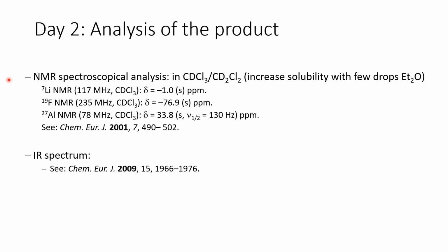The product should be further analyzed by NMR and IR spectroscopy. The NMR can be performed in deuterated chloroform or deuterated dichloromethane. Here it's often beneficial to add a few drops of the ether to increase the solubility of the lithium salt. In the NMR, characteristic signals of lithium, fluorine, and aluminum can be detected. Further information can also be found in our original publication. The IR spectra of a variety of salts of the perfluorinated aluminate anion are discussed in the chemistry paper of 2009 from our group.